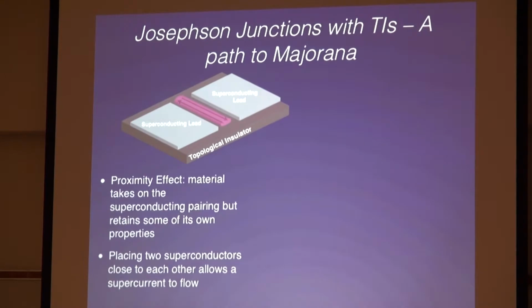So what are we going to do with this material system? Bismuth selenide, you'll take a topological insulator and you'll put a superconductor on top. And if you can make this interface between the superconductor and the topological insulator good enough, some of the superconducting properties will leak into the topological insulator. And if you put two separate superconducting leads near each other, the leakage of the two superconductors can overlap, and you can actually pass a supercurrent through here.